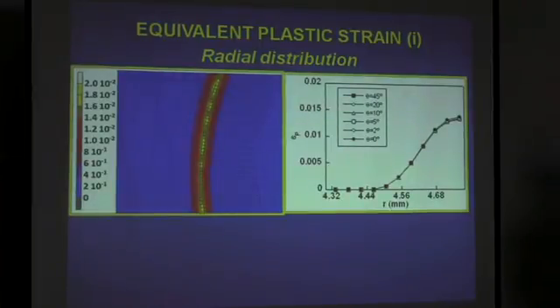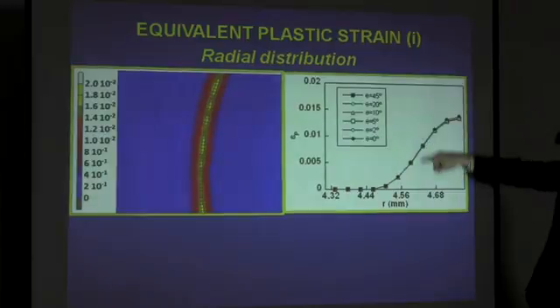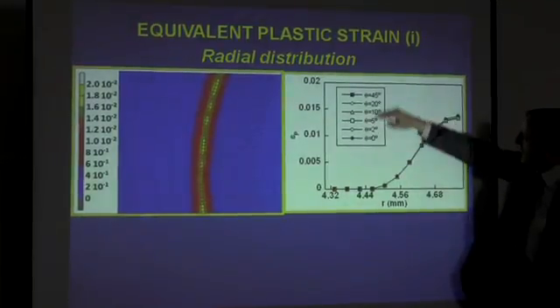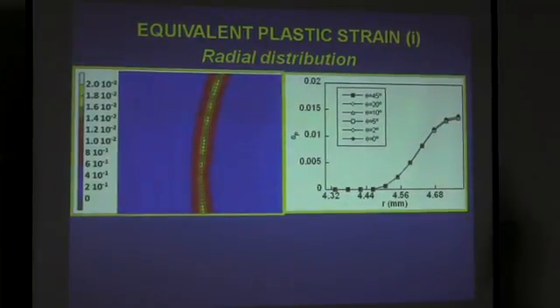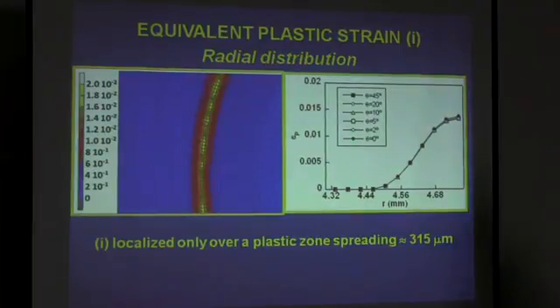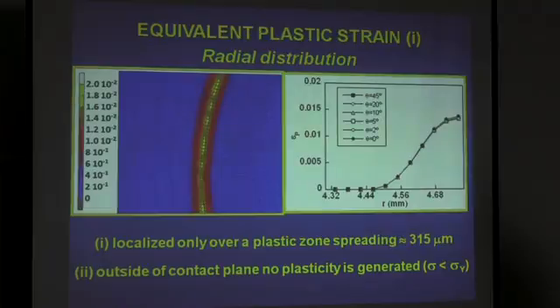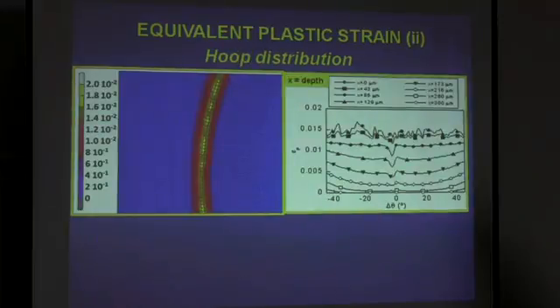The radial distribution with concentration in the contact area, but no difference between the different angles. It seems that it is accumulated over a ring, and it does not strongly depend on the angle. Localized only over a plastic zone spreading of, roughly speaking, 300 micrometers. Outside of contact plane, no plasticity is generated. We are below the yield strength of the material.